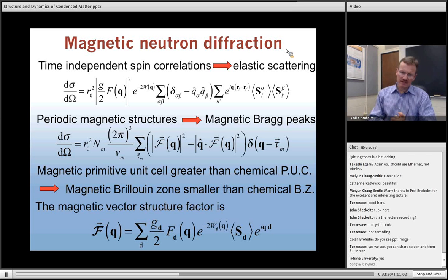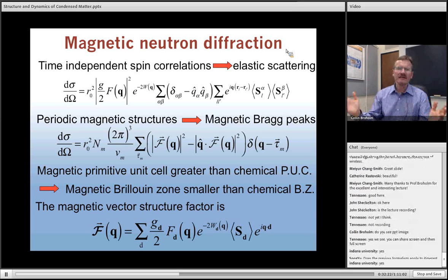Of course, if I have a paramagnetic state or a spin liquid state that we'll be talking about later, then this correlation function may not have a finite value when time goes to infinity. It may actually vanish. In fact, most materials which are not magnetically ordered would not have a finite limit to that two-point correlation function in the time-goes-to-infinity limit.